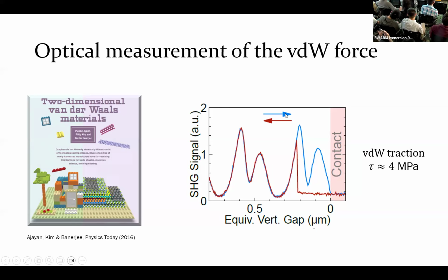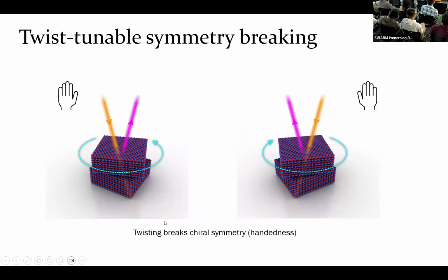When we scan the voltage back and forth and back and forth, we're seeing this reproducible hysteresis loop. And from the size of that loop, we can calculate and estimate what the van der Waals traction is. So it's estimated to be about 4 megapascal in this device. Okay, so far we haven't really started to use the rotating part of the MEMS device, right? So now let's look at that.